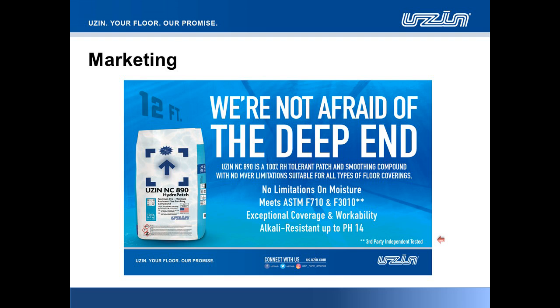So we listed every relevant property that we thought might be affected in this patch, and we elected to test the product not only in elevated moisture but simply underwater, because that's easy to control and it ensures the maximum exposure to moisture. And that was the project. We spent over 2 years developing the formulation, and that led to some breakthroughs in the choice of specialty cements, polymers and other additives that help the patch retain its integrity underwater. It does not fall apart. It does not lose compressive strength. It actually builds it.